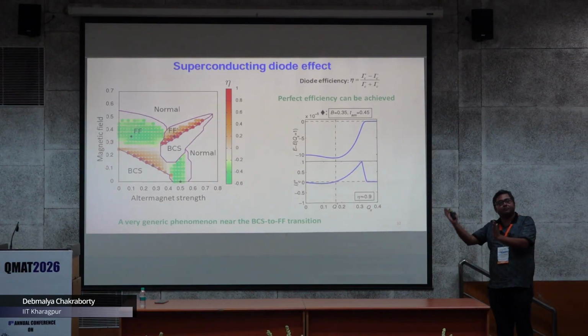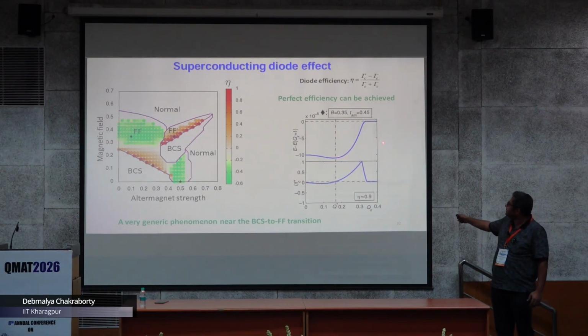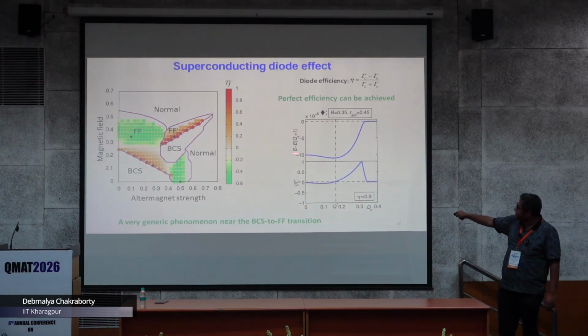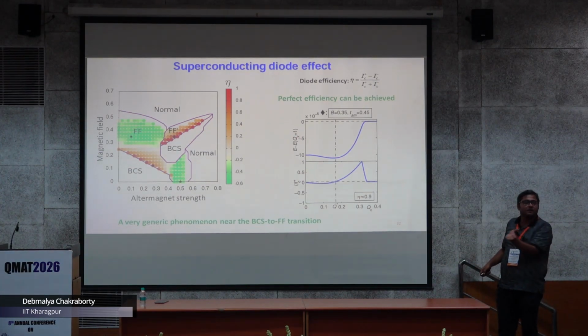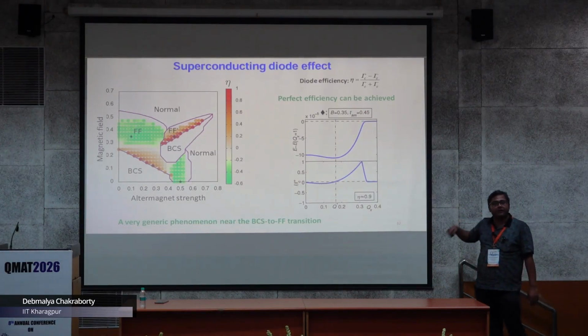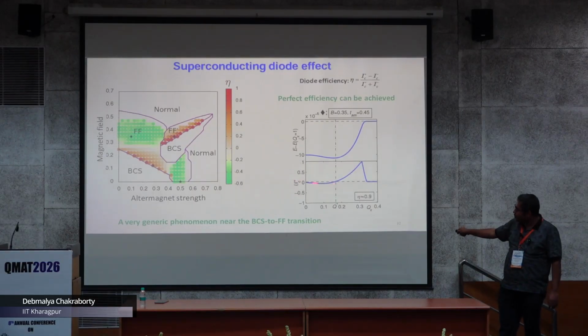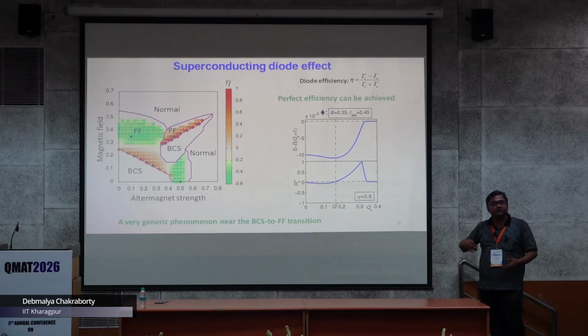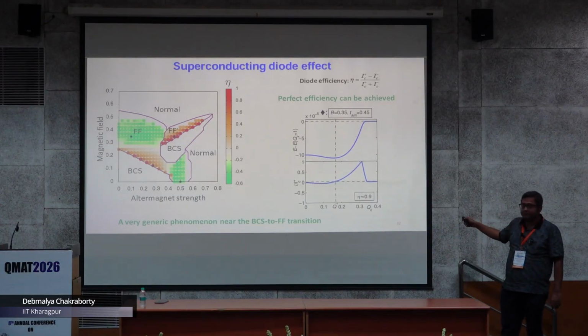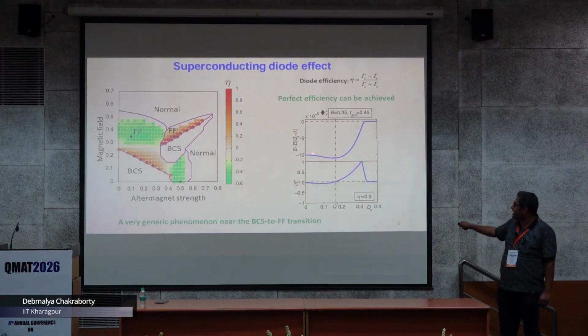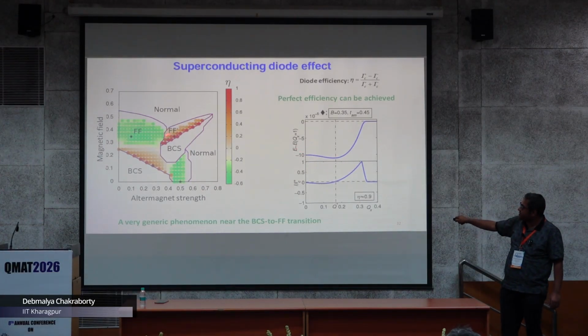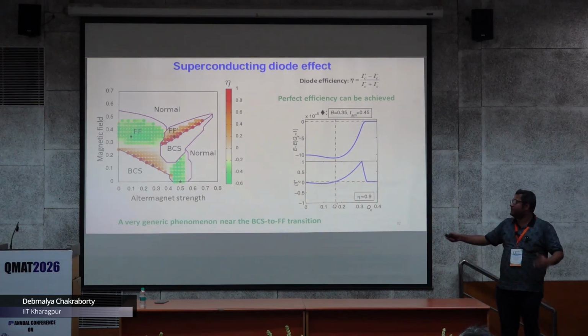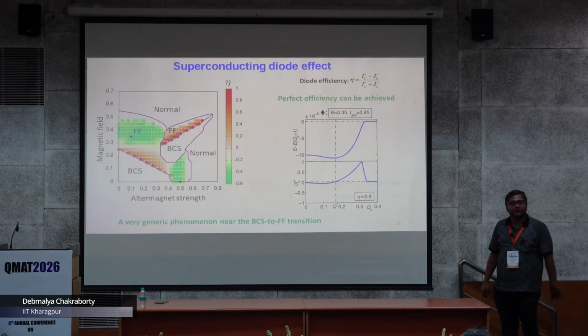Now if I look at a plus Q and a minus Q, that means in this direction and in this direction, you can already see that the slope in this direction is very flat and it's quite steep in the other direction. That means the derivative, which is the critical current, will be very low in one direction and very high in the other direction. So the efficiency will be very high. This is happening because Q equal to 0 has a very weak minimum and energetically they are very similar. Near this transition, they actually cross and become equivalent, and as a result it's a flat thing.